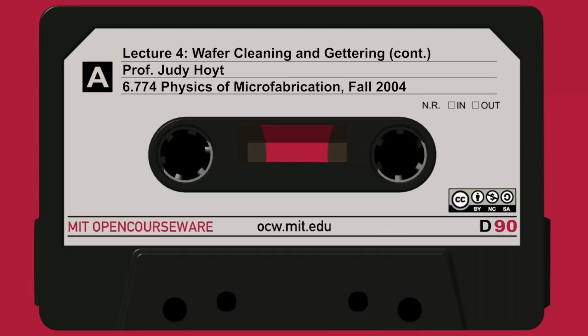No one's been able to actually measure it exactly, because you can't see a silicon interstitial, so you can't profile how rapidly it diffuses, but there are indirect ways of inferring it. So somewhere in this brown band is where the silicon interstitial diffusivity lies. It's not bad. It's not as fast as the fastest metals, not as fast as copper or interstitial gold or iron, but it's in the range of some of the metals.